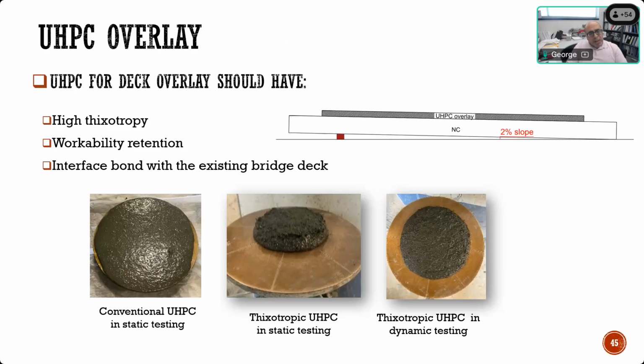So you need to make a special kind of UHPC that is called highly thixotropic, which means if you don't agitate it, it stays stiff, but if you agitate it or vibrate it, it basically continues to flow. That required changing the mix or developing a new mix that has high thixotropy and also has workability retention, in addition, of course, to having good bond with the existing concrete. The picture on the left is the one we presented earlier. But for UHPC overlay, we did another mix that doesn't flow under static testing, but it can spread and flow under dynamic testing. And that's a different type of behavior that is needed for that application.